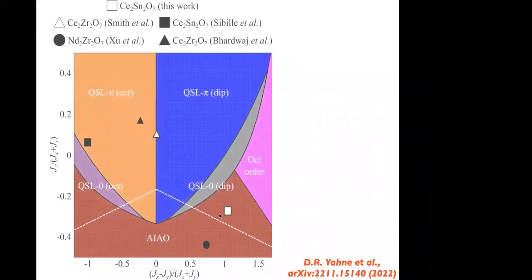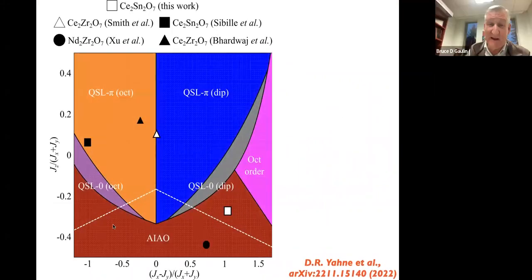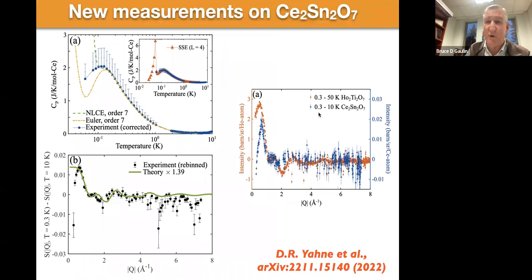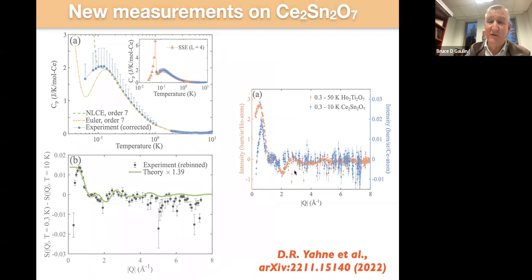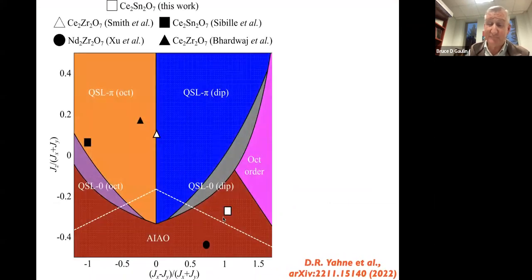That's because it's being placed in this red region, which is a dipolar ordered all-in, all-out ground state. But at the temperatures that we're measuring, which are 0.3 Kelvin, we actually see something that looks like dipolar spin ice. So what we believe we're seeing is a proximate dipolar spin ice above an ordered ground state, which would be dipolar all-in, all-out.